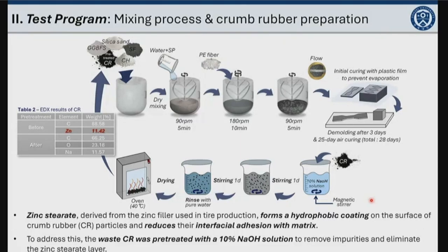To address this issue, the waste crumb rubber was pre-treated with a 10% sodium hydroxide solution to remove the zinc stearate layer from its surface. The detailed process is shown here.